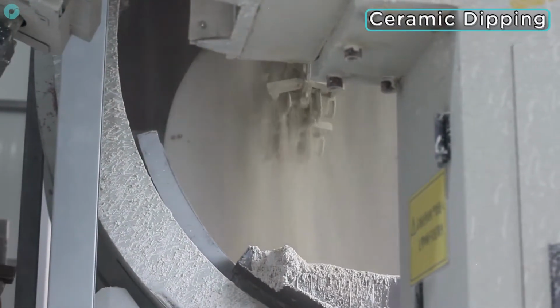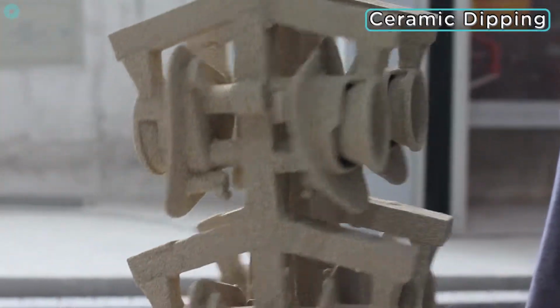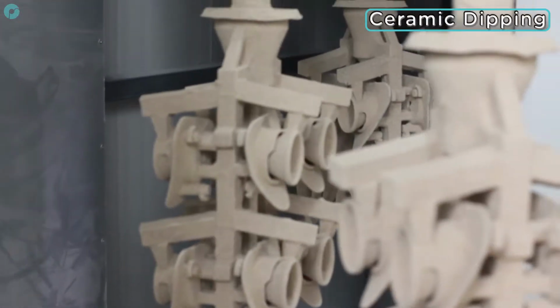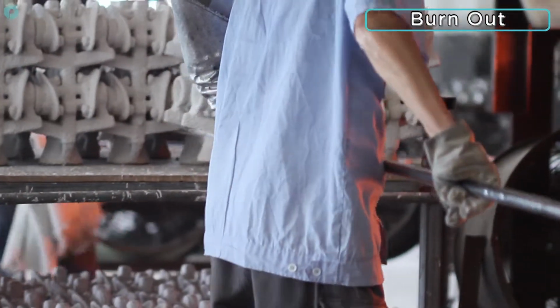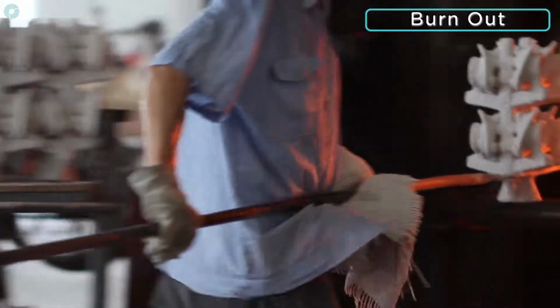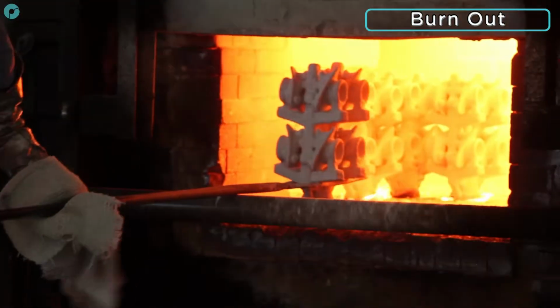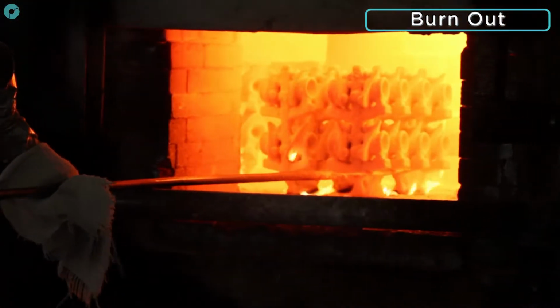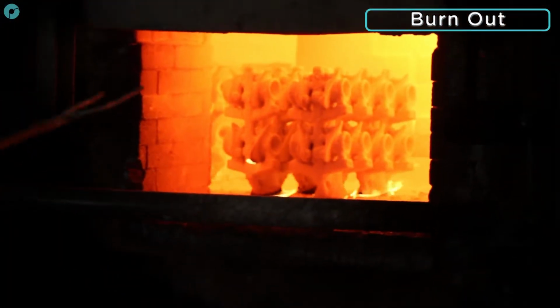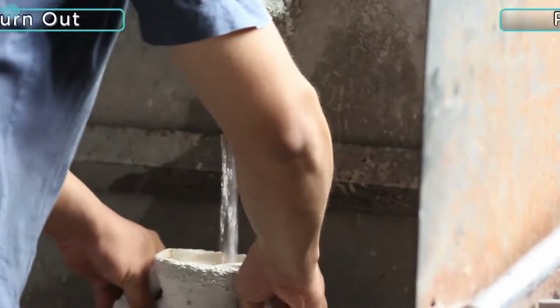The moulds are then transferred to the kiln for the curing and burnout process. The moulds are placed upside down in the kiln at a temperature of 900 degrees centigrade. This fires the ceramic and cures it ready for moulding. The PolyCast patterns are completely vaporized during this phase, leaving a clean investment mould.